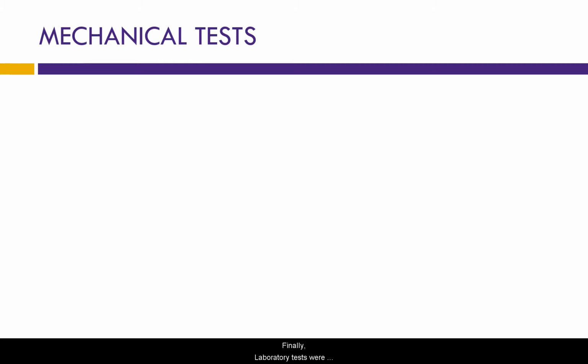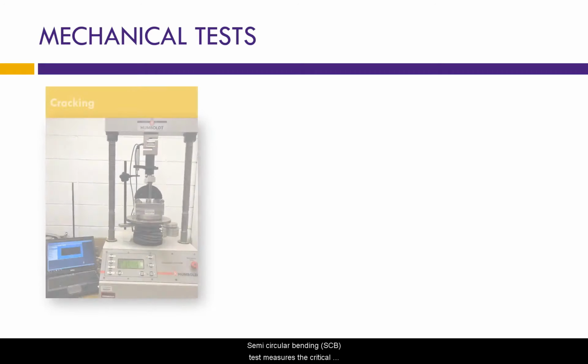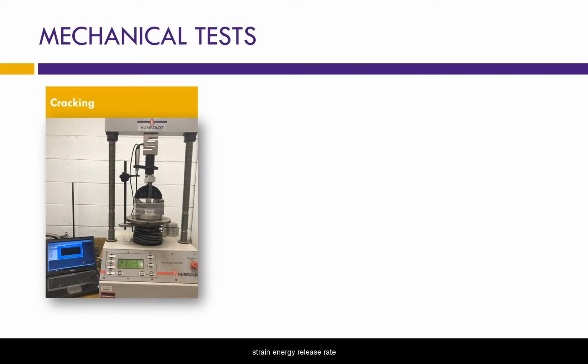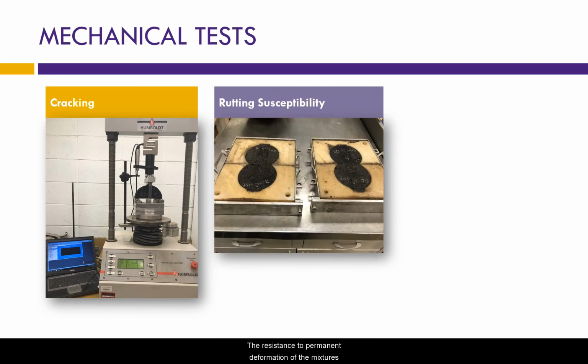Finally, laboratory tests were conducted to study the performance of asphalt mixtures containing the optimum percentage of self-healing polymer against cracking at intermediate and low temperature and rutting. Semicircular bending test measures the critical strain energy release rate to examine the cracking performance of prepared mixtures at an intermediate temperature. The resistance to permanent deformation of mixtures was evaluated using the LWT, where cylindrical specimens were submerged at 50 degrees C, and a steel wheel was passed across the surface until attainment of 20,000 cycles at a rate of 56 passes per minute.